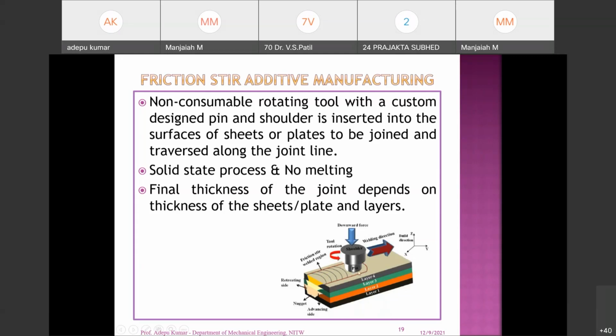So the material movement takes place and fills the gap at the backside of the pin. That's why the weld is formed. So material flow plays a very important role. The material flow is a function of various parameters like rotational speed, welding speed, tool diameter, pin diameter, tool material, and work material. So many factors govern your material flow.